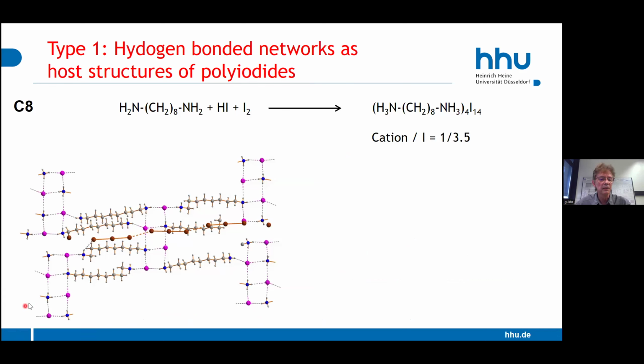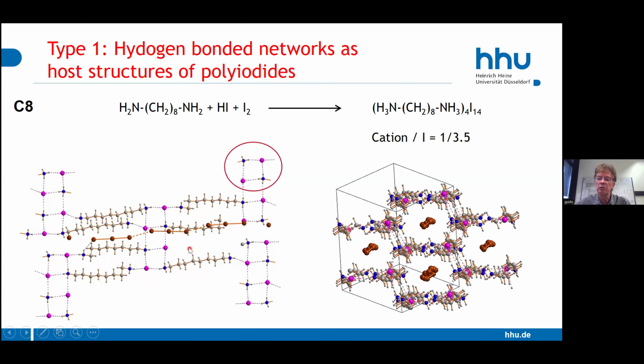It's a C8. I lost my cursor, my spotlight. Okay, we have a C8 organic molecule which is connected to an iodide, and then we obtain these square hydrogen bonded motifs which are connected to each other, and these parts of the structure are then connected to the next chain of these squares. This creates a framework, and in this framework we have channels, and these channels are filled with a polyiodide. You see here.